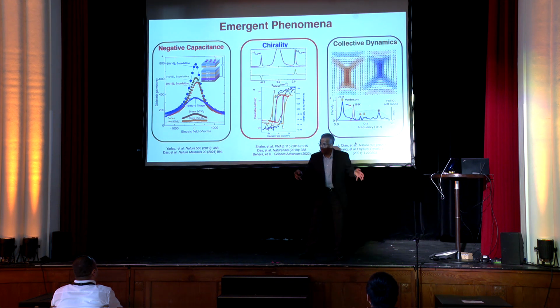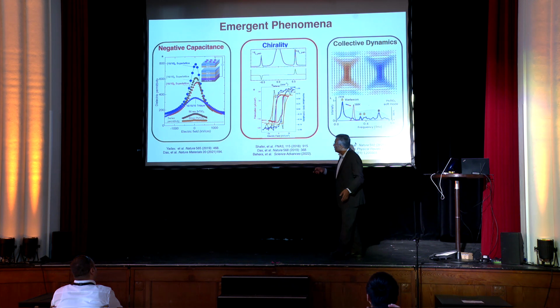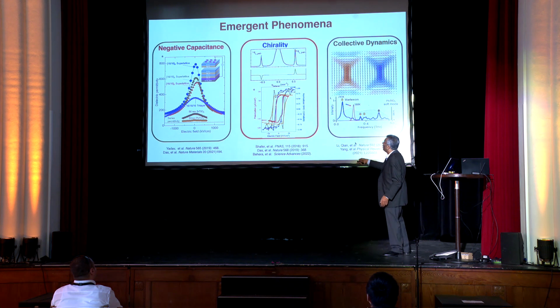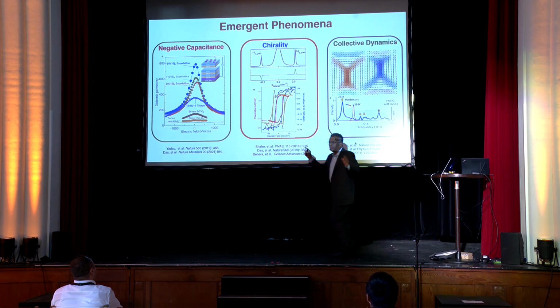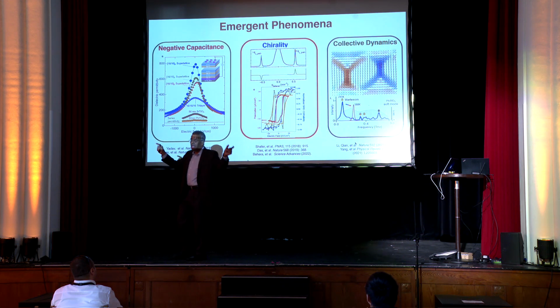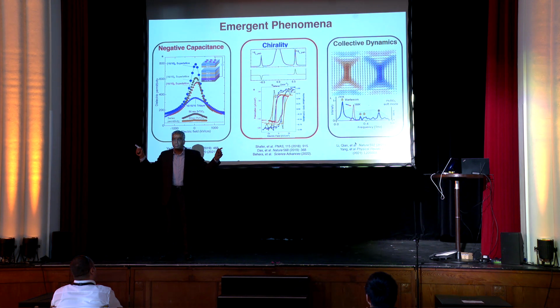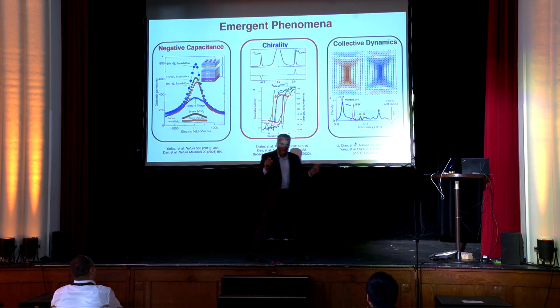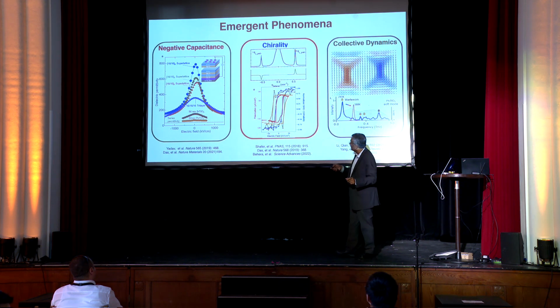It can happen in local regions, not over the entire volume of the material. So you can trap in negative permittivity and get large effects on that. You also have handed behavior. You take two materials, lead titanate and strontium titanate. Neither one of them is chiral. You put them together in a certain way and get these vortex or skyrmion-like structures. You can start to pick up handed behavior.